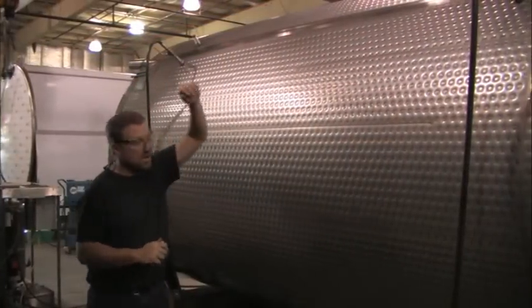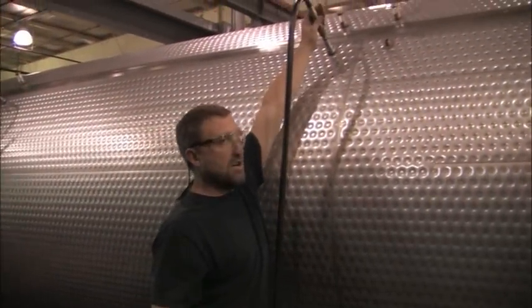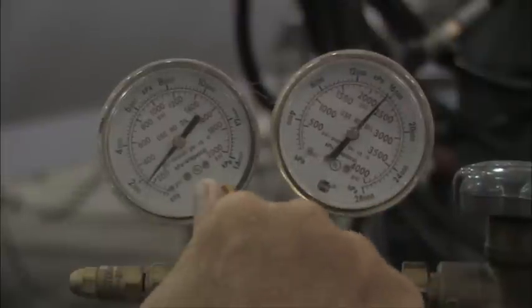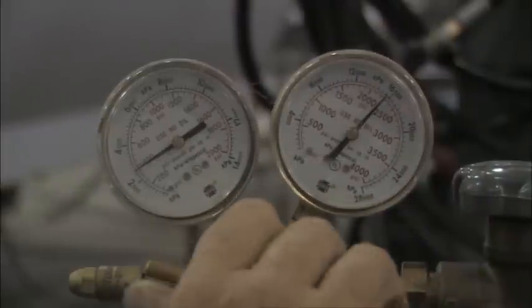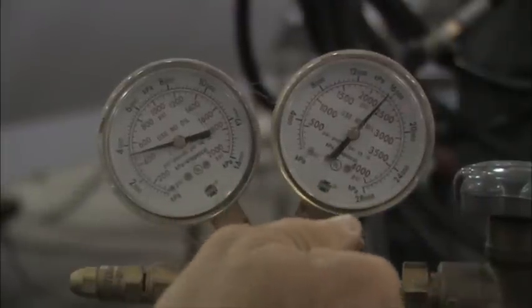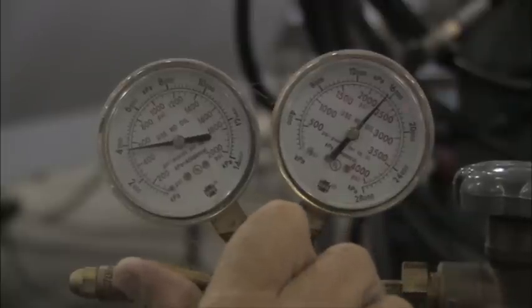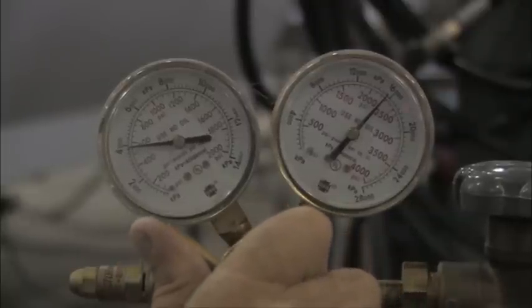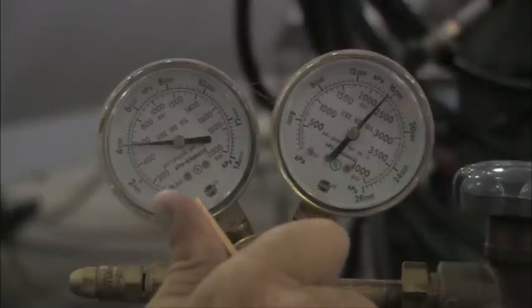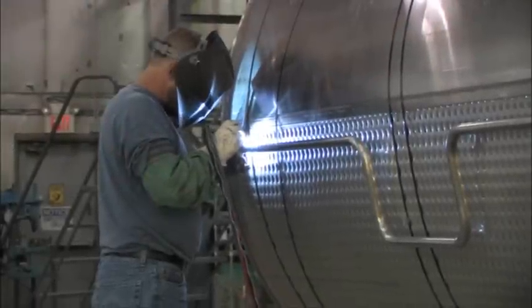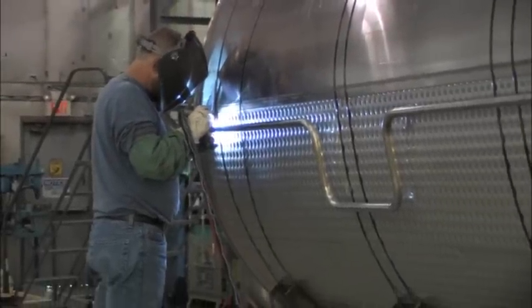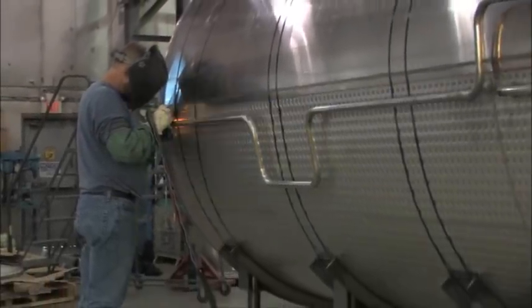We pressurize the evaporators with dry nitrogen gas at 560 psi to create an 80,000ths of an inch space between the inner and outer surfaces for the refrigerant. We maintain that pressure for 15 minutes and measure any pressure losses indicative of leaks. The inflated panels are then filled with refrigerant oil containing a fluorescent dye to test for minute leaks using an ultraviolet lamp. Stainless steel refrigeration lines are then installed and the entire system is tested again for leaks using the UV lamp.